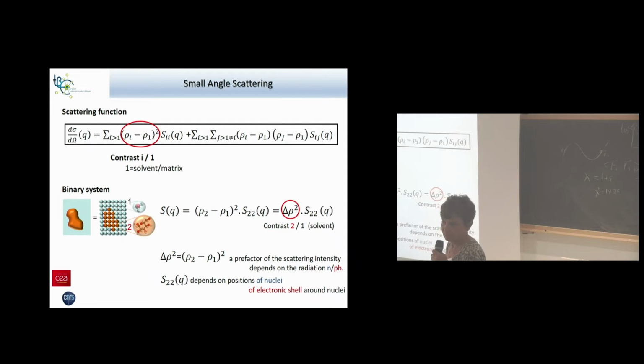What is the physical significance of Q here? Q is a scattering vector. Does it signify the length scale of scattering? Yes, inverse. Q is the inverse of the length of observation of the sample. Small q means you are looking at large fluctuation, and large q means you are looking at small scale fluctuation.